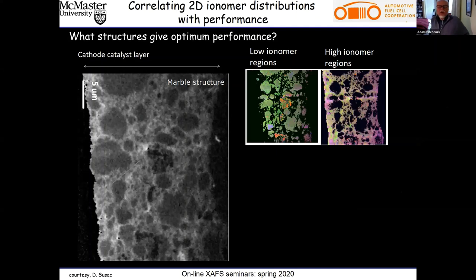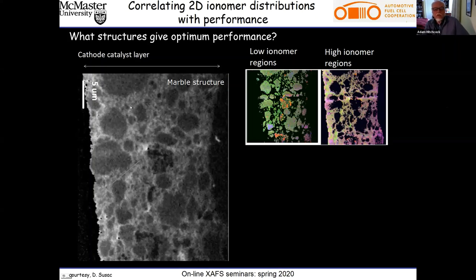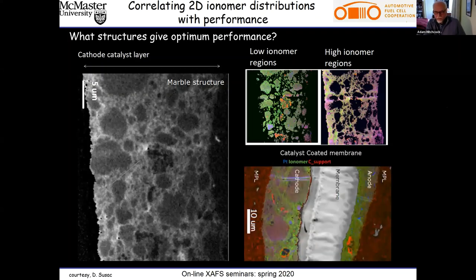This idealized system shows very uniform ionomer distribution—exactly what industry wants. The capability to analyze not just qualitatively but quantitatively, because response functions are in an absolute sense, gives a lot of value added as manufacturers modify fabrication procedures. AFCC were puzzled by a mottled pattern in some cathodes, initially thinking lighter-colored regions were bunching of carbon support based on electron microscopy. What the electron beam was actually doing was removing the ionomer—so what they thought was carbon morphology was actually an ionomer map.